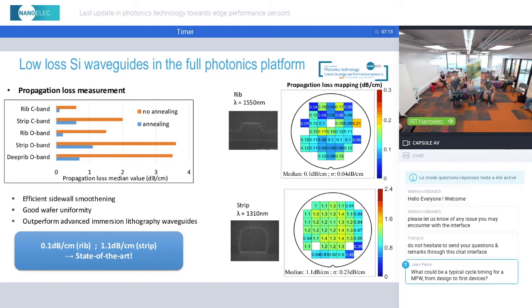Okay, so let's see now the results in terms of propagation losses. In the plot on the top left of the slide, you have the propagation loss measurements for rib, strip, and deep rib waveguides in both spectral bands that we are interested in: C band, around 1550 nanometers, and O band, around 1310 nanometers. The loss reduction by applying the annealing treatment is really spectacular. For example, for rib waveguide in C band, we go from 0.7 dB per centimeter without annealing to 0.1 dB per centimeter with the annealing.